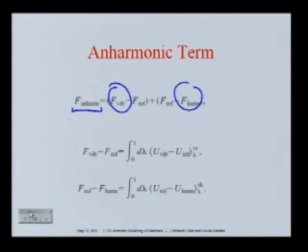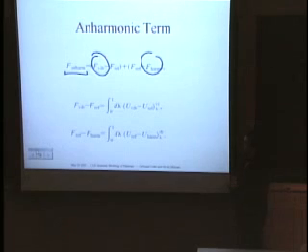So basically, with all this formalism, what one is able to do at the end is calculate free energy differences, in which the fundamental components are calculating the phonon frequency of your system, in this case specifically for the case of a solid, that gives you the first step in the vibrational free energy, and is nothing else than, in this case, a density functional perturbation theory calculation.